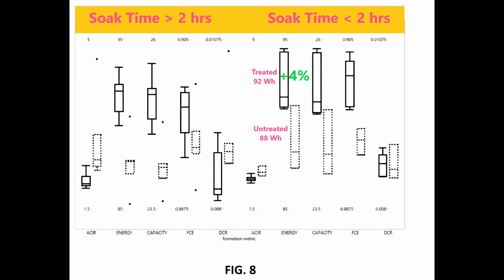Regardless, the implication here is that with a plasma treatment process, Tesla may have accidentally found a way to squeeze a few more percentage points of energy density out of their batteries, or even skip formation steps. It's difficult to say because Tesla tested treated versus untreated dry-coated battery cells, and we don't have a comparison against wet-coated cells using a conventional formation process.